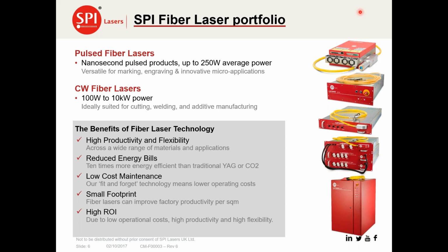That's over 3 orders of magnitude of tunability. And that has a corresponding effect on the peak power available in these pulses and the pulse energy. But at the end of the day, many of these applications are about the average power that is available. And it's amazing how much a 200 or 250 watt laser can achieve in terms of productivity. Then we have the CW or continuous wave fiber lasers, and these are available from 100 watts all the way up to 10 kilowatts and are more traditionally used for cutting and welding applications and also for additive manufacturing.